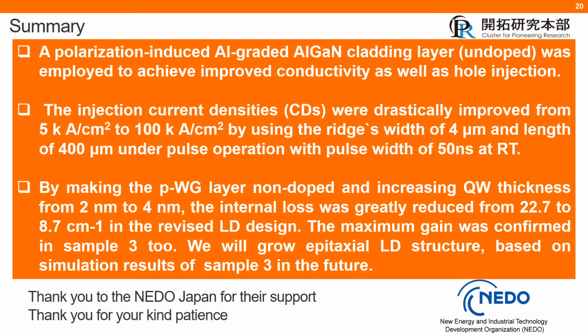A polarization-induced aluminum-graded AlGaN cladding layer, which is undoped, was employed to achieve improved conductivity as well as hole injection toward the quantum well. The injection current density was drastically improved from 5 kiloamps per centimeter square to 100 kiloamps per centimeter square at 285 nanometer emission wavelength, using a ridge width of 4 micrometer and length of 400 micrometer under pulse operation. By making the P waveguide layer non-doped and increasing the quantum well thickness from 2 nanometer to 4 nanometer, the internal loss was greatly reduced from 22.7 to 8.7 centimeter inverse in the revised design.